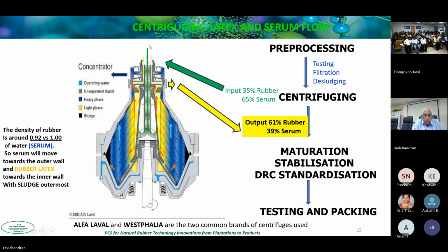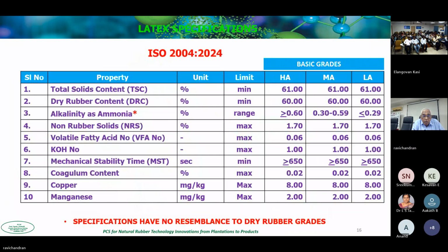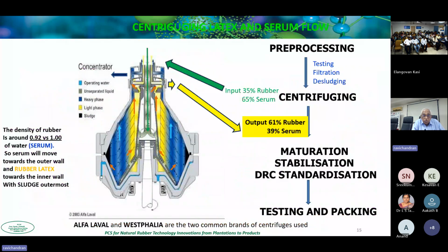So the field latex comes in to the center, and then the centrifuge is spinning at about 10,000 RPM. Because the density of rubber is 0.92 and water, the serum, 1, the heavier goes to the outside. That's a blue color. And the latex comes through the inside. There are a whole lot of discs through which this goes. And the yellow part is the latex coming out, and the output. The input is 35% rubber and 65% serum. The output is 61% rubber and 39% serum.